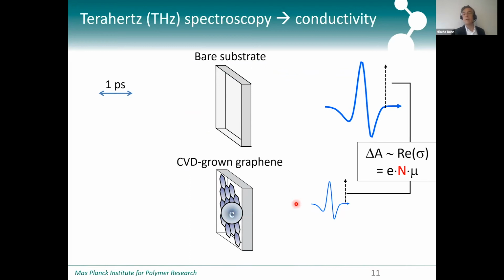And so the quantitative nature of this technique is that the change in the amplitude is a direct measure for the number density and the mobility. So it's the product of the number density and the mobility. And the phase shift that you see here, so there's a time lag between the two, is proportional. The amplitude is the real part of the conductivity. This phase shift is the imaginary conductivity, which is none other than the polarizability. So the difference in refractive index, because there is some real conductivity.